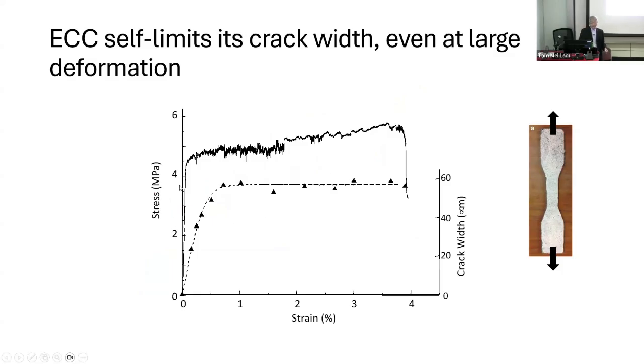So a little bit more about the damage behavior of these materials, the same elastic and then strain hardening behavior of ECC. And what I'm showing you here on the right y-axis is the crack width development. So this is very interesting. Notice that as I increase the strain in this tensile specimen, the crack width starts to increase, going from 0 to about 60 micron here, okay? And then what is very interesting is that if you continue loading, keep pulling and stretching the material all the way up to 4% strain here, the crack width remains about constant. How about that? So even at large deformation, the cracks remain very tight.